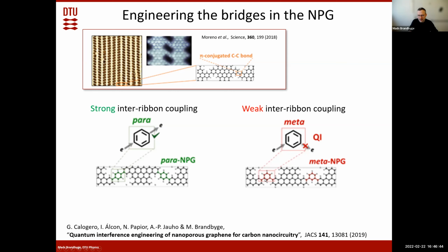And that means that the path the electron takes in the upper part of the ring or in the lower part of the ring is differing. And it's differing by half a wavelength, roughly. So that means you have a quantum interference between these two paths. And that means that this ring, when you connect a benzene ring in this way, is really not conducting very well. So by changing the bridges, we can change the conduction or the coupling between the ribbons.